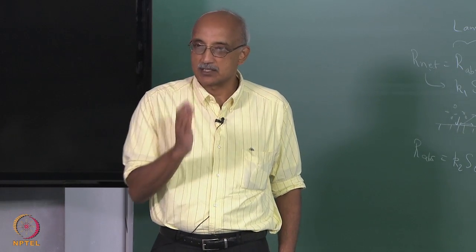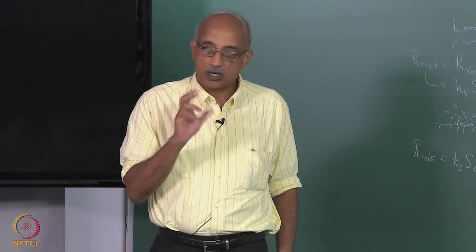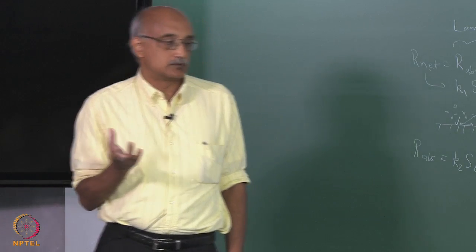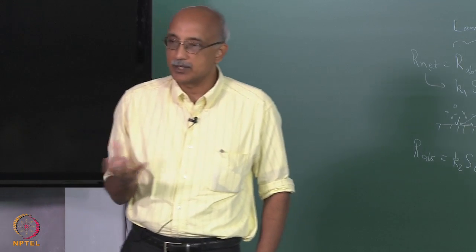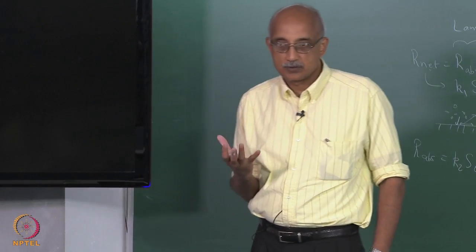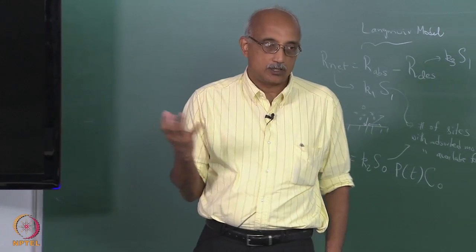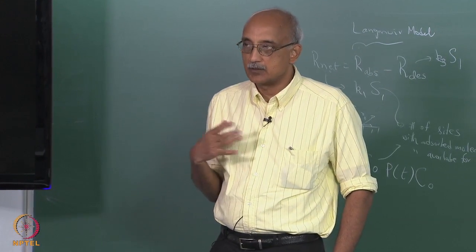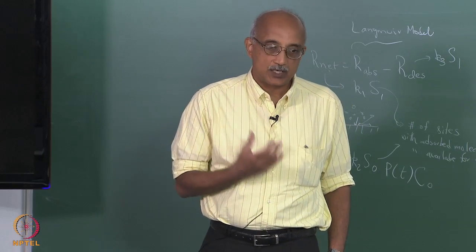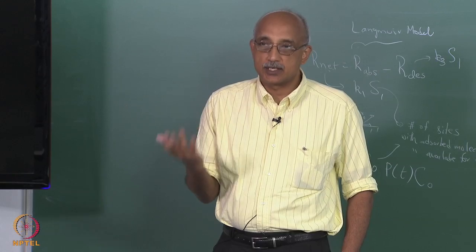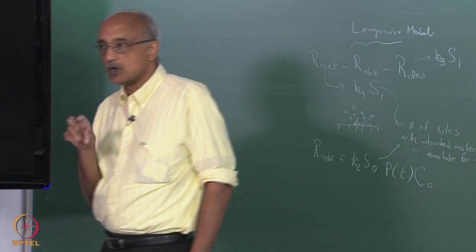You want to be right in the center, so that even if there are small changes in the concentrations of the dopants, it is not going to prevent the dopant from being incorporated into the film. A classic example would be a silicon film where you want to incorporate phosphorus as a dopant, or another case we looked at earlier, the silicate, borosilicate and phosphosilicate glasses, where you try to incorporate boron and phosphorus into silicon dioxide.